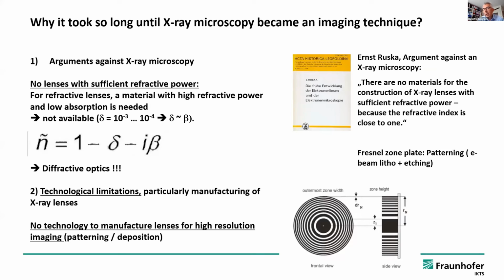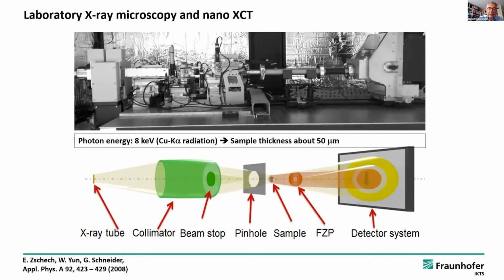However, if you would like to get 50 nanometer resolution, the thickness of the outermost ring has to be 50 nanometers. And to manufacture them is not easy. You need technologies from microelectronics, and they were not available for a long period of time. So we had technological limitations. And these two reasons are reasons why X-ray microscopy has been only available for a couple of decades.